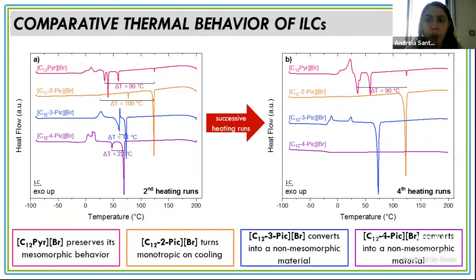In order to compare the thermal behavior of all ionic liquid crystals prepared, the left figure includes the second heating runs for each material, and it's possible to observe that C12 pyridinium bromide is the one that exhibits more liquid crystalline transitions, having 3. It also has a large LC window, and C12 2-picolinium bromide has 2 LC transitions and also a large LC window. For C12 3-picolinium bromide and C12 4-picolinium bromide, only 1 LC transition was detected with a small LC window. It is possible to observe that the position of the methyl group impacts the isotropization temperature, decreasing from 124 to 70 degrees.